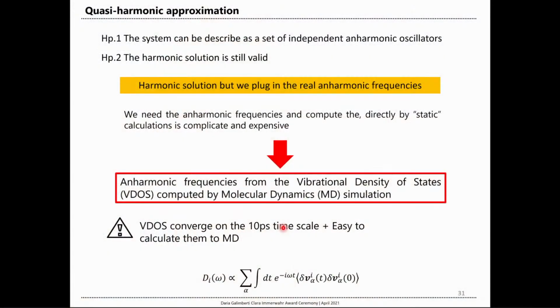However, there are other properties that can be computed by molecular dynamics simulation on a much shorter time scale. In particular, an interesting one is the vibrational spectra. Vibrational spectra can converge in a time scale between 10 and 20 picoseconds. And as you can imagine, the vibrational spectra obviously have the information that we want, that is, the anharmonic frequency. In particular, this information can be stored in the vibrational density of states that can be really easily calculated by a molecular dynamics simulation. And so we have a way to find this anharmonic frequency with a short simulation.